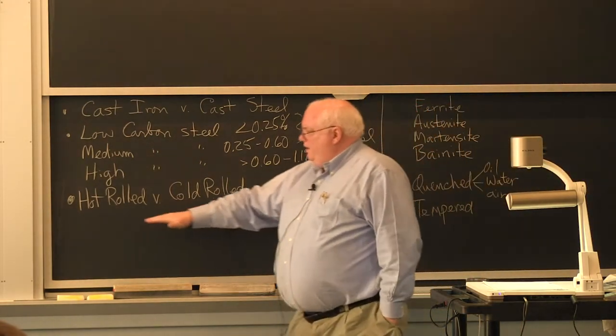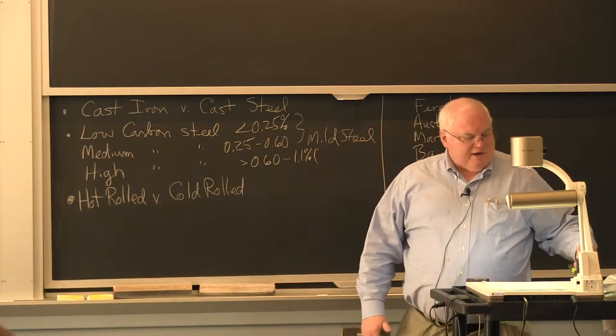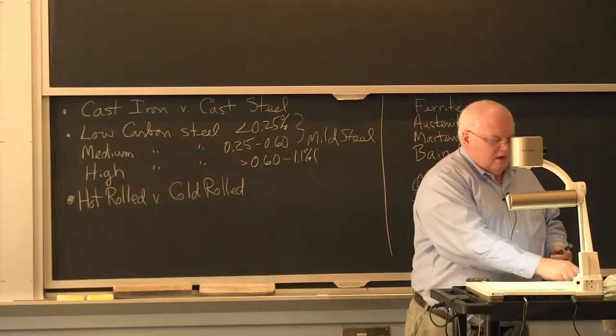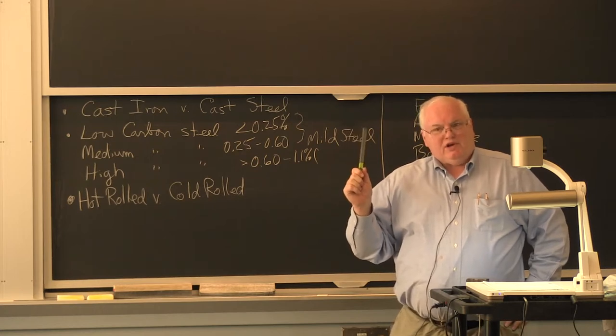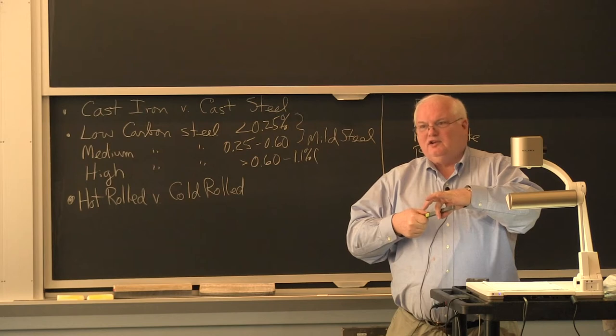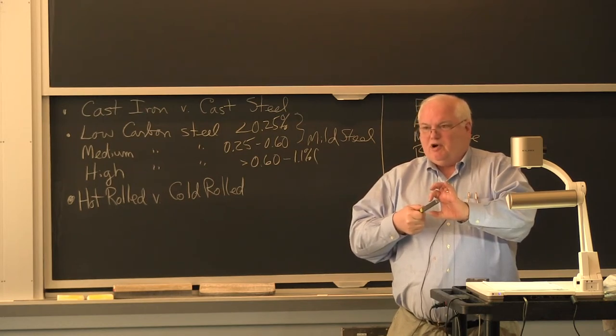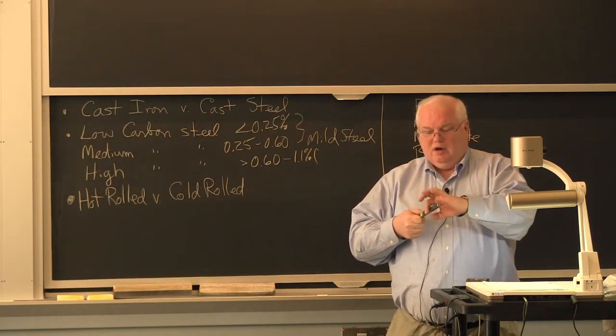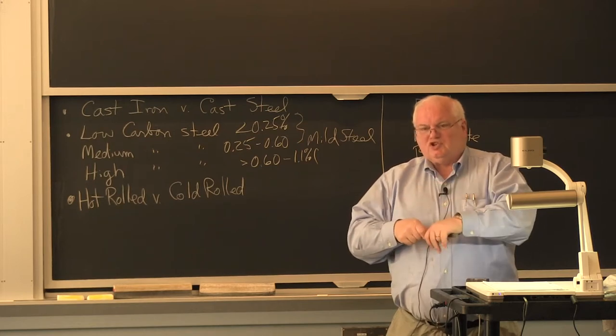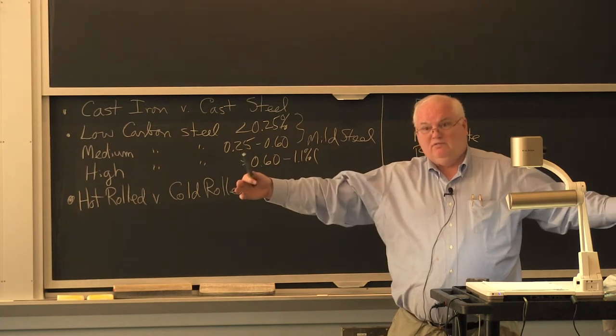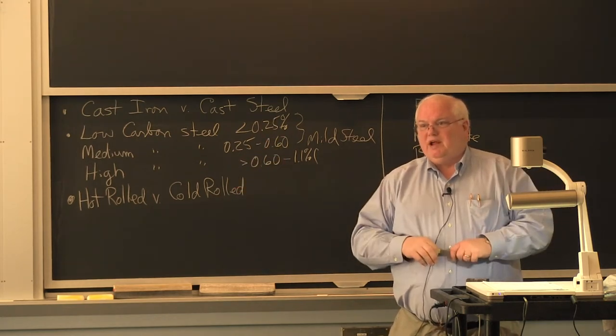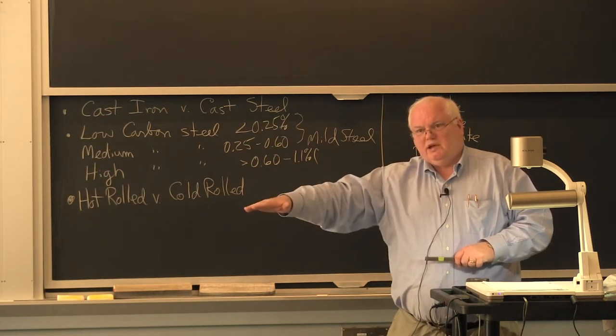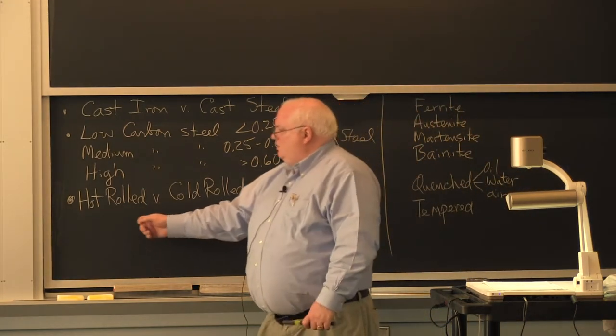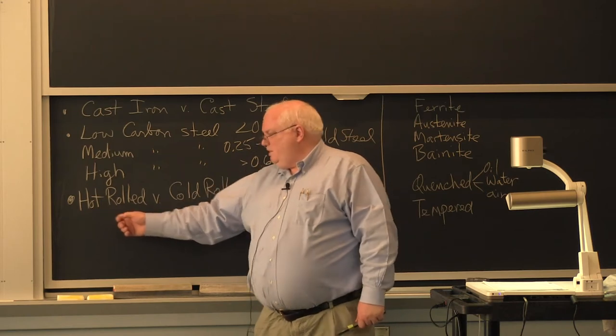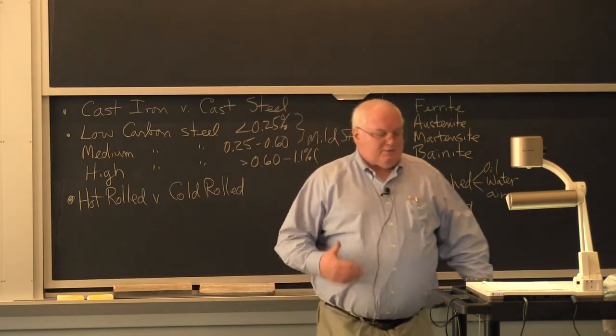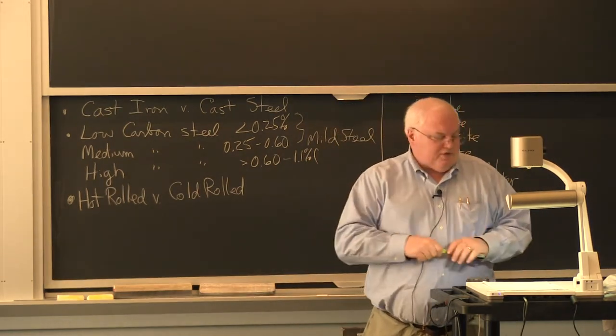So when you say hot rolled and cold rolled, now, if you're talking bar stock, I can have half inch bar stock, like this stuff. It's got a magnet in between. What do you know? I can have something like this half inch bar stock. That could be cold rolled because the mill to squeeze that could do it cold even though it's a half an inch. It might have started out with something that was bar stock of inch or inch and a half, round or square. And a mill can have enough separating force to squeeze this cold down to this. But if you're talking a big wide plate, 5 feet wide, we just don't have mills big enough to have the force necessary to squeeze that plate if it's more than a quarter of an inch thick. So hot rolled, if we're talking plate material, plate comes off the hot roll basically, sheet comes off the cold roll, okay? And it's basically just a question of thickness. When you get to bar stock, you can be a little bit thicker in the cold rolled.